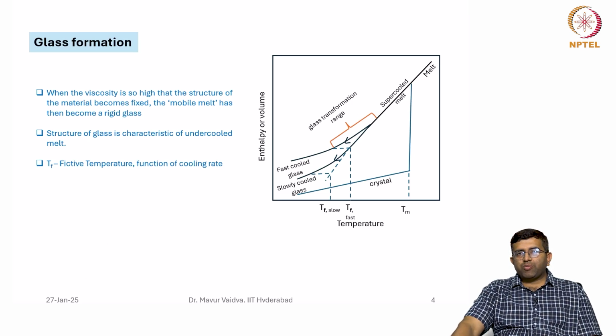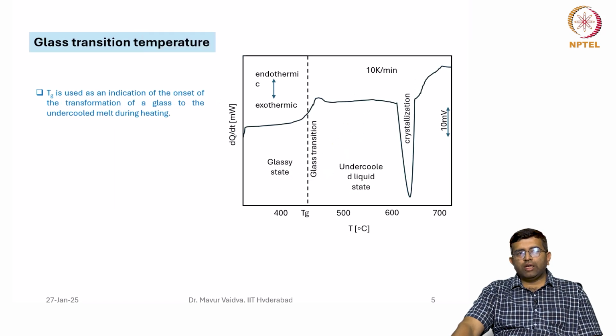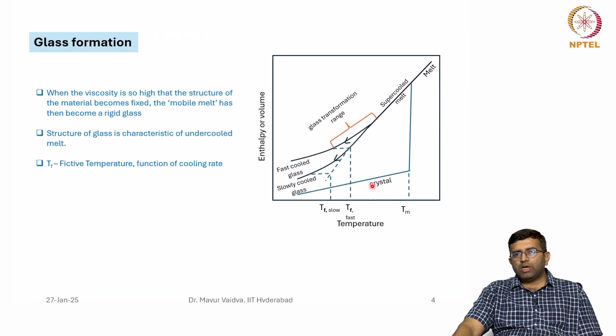So, this fictive temperature is a function of cooling rate. How fast you cool matters: when the cooling is fast, the fictive temperature is higher, which means you can form the glass quickly. When it is slow cooled, the fictive temperature is lower, and therefore you have to bring it down to a lower temperature for the glass to form.